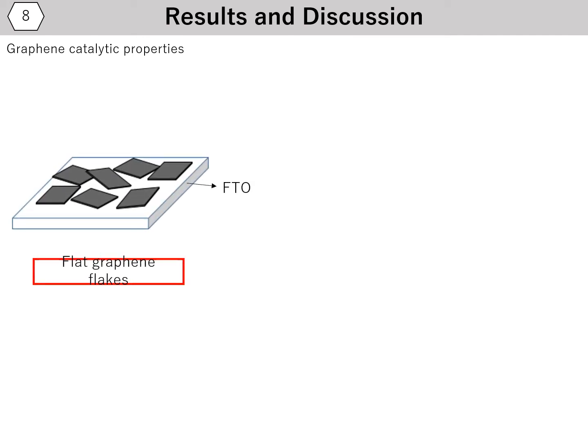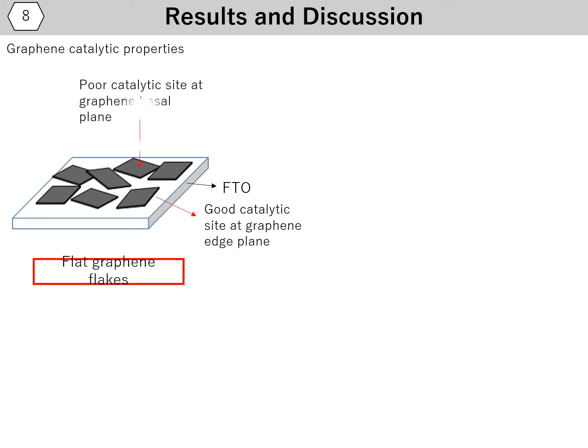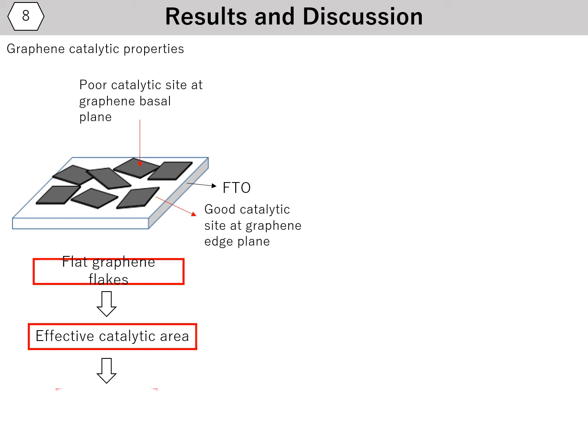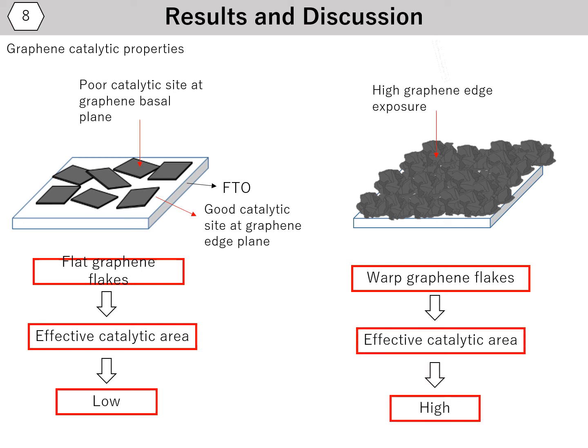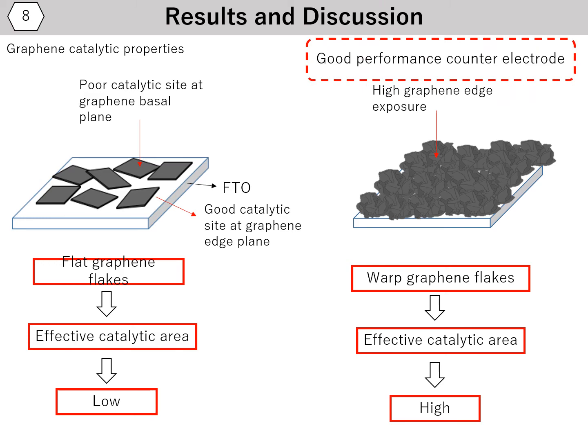In graphene catalytic properties, the graphene edge plane has good catalytic site and the basal plane has poor catalytic site. So when we deposit flat graphene plates, the effective catalytic site area is low. This is different when graphene plate is wrapping titanium dioxide nanoparticle. It will result in warped graphene flakes with high graphene edge exposure with high catalytic area. So it will have good performance for counter electrode.